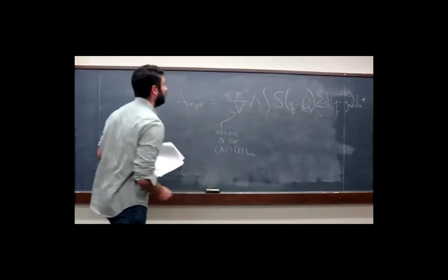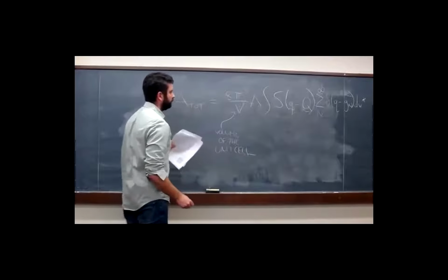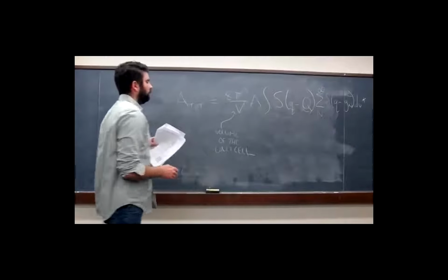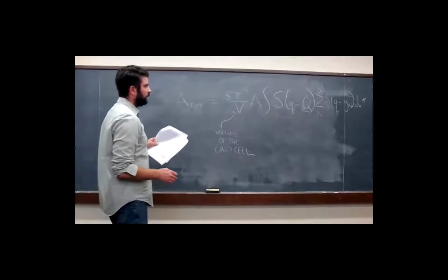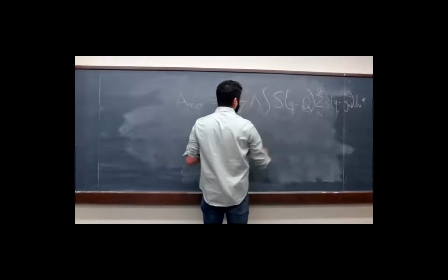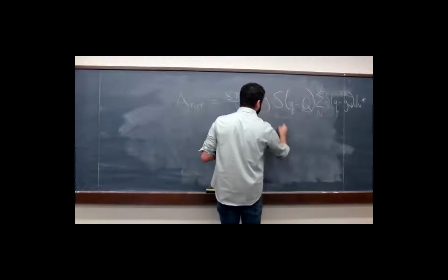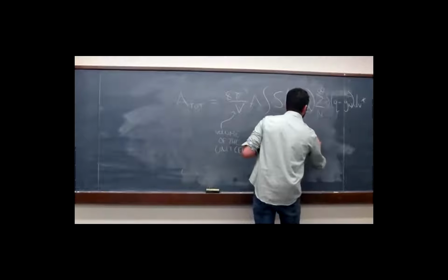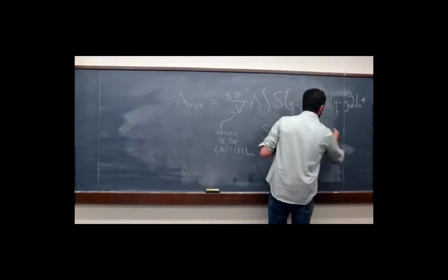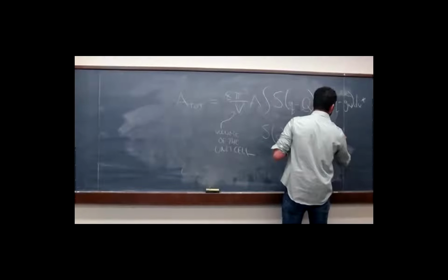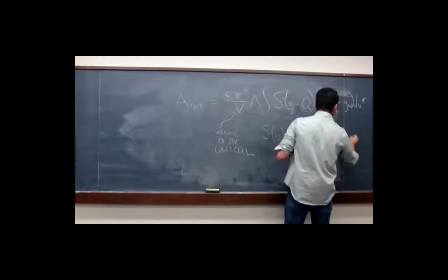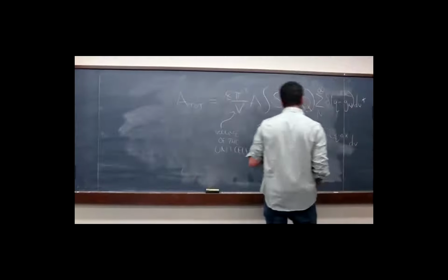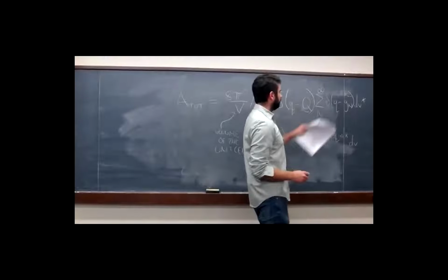Okay, so we've got these prefactor terms, but what we have here is a convolution. We talked a little bit on the first class about convolutions, but essentially this is a tiling operation. I've got this big S(q) here, which is just the Fourier transform of our shape function, tiled over the reciprocal lattice points.